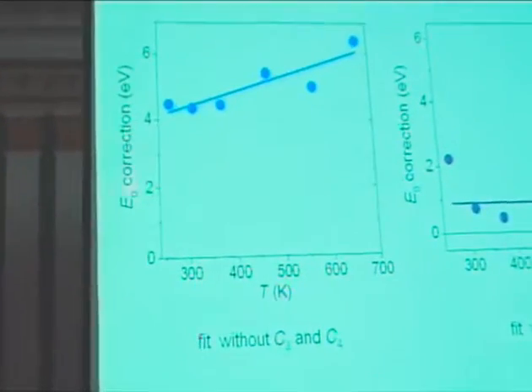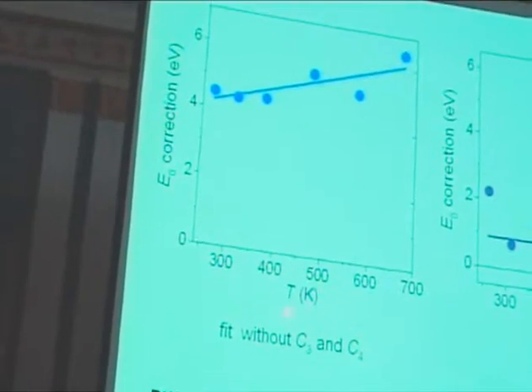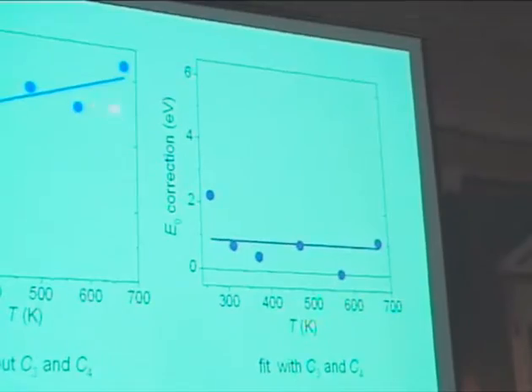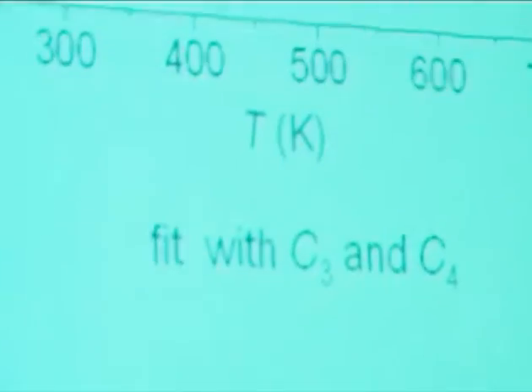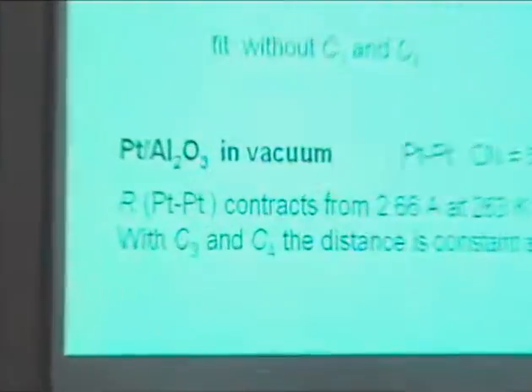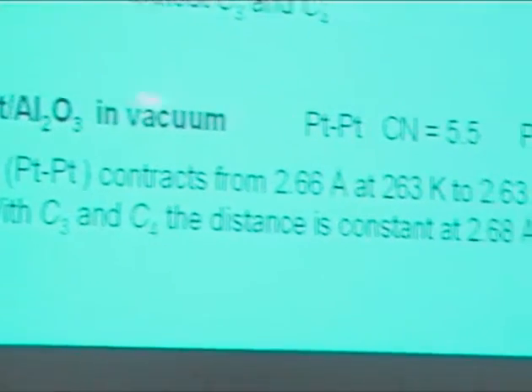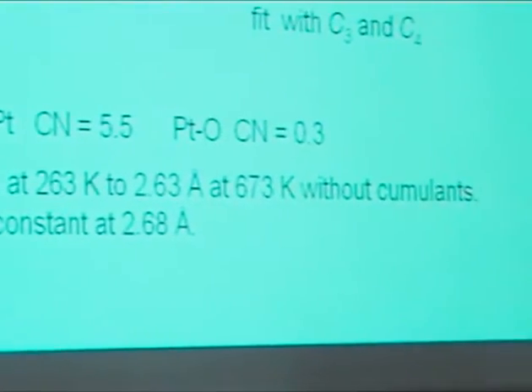For instance, here we have a fit for the E0 correction in the EXAFS without and with. And you see that without, I have to go to quite high, technically too high, E0 corrections, also varying with temperature, which is physically nonsense. And when I do include the higher order cumulants, which means I go to a skewed distribution, then everything is all right. I'm talking about a platinum on alumina here, measured in vacuum.